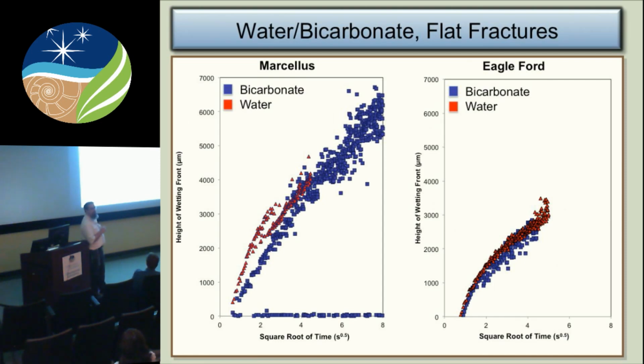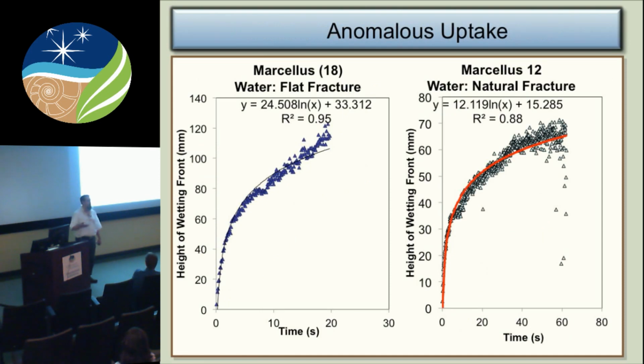The theory of capillary uptake, or flat plate between two plates, would suggest this should be, it's a diffusion process. It should be linear as a function of the square root of time. And if you saw these before, obviously this is plotted as a square root of time. You can see that it is not linear as a function of square root of time. In fact, it's something close to, but not exactly, a logarithmic behavior. This is, again, probably because of this interaction between the shale and the uptake. This is known as anomalous diffusion or anomalous capillary flow.